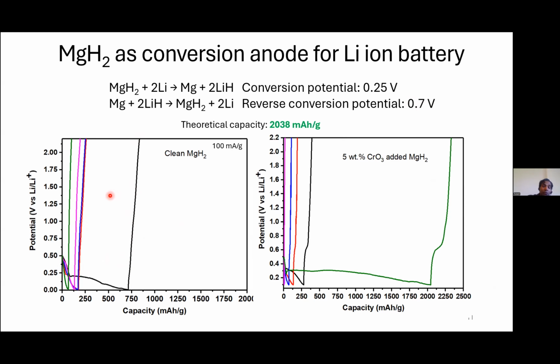Then again, we have to call upon the help of activators, catalysts. Okay, we have used an interesting catalyst, chromium trioxide in a 5 wt.% concentration, and experiments were repeated under identical conditions. And what happened? This one happened. The forward conversion almost reaches the theoretical capacity. And what about the reverse conversion? Reverse conversion happens, almost close to the potential suggested theoretically, but not fully, only partially. And in the further cycles, it decreases again. At a particular stage, in 5 cycles, the battery is dead.